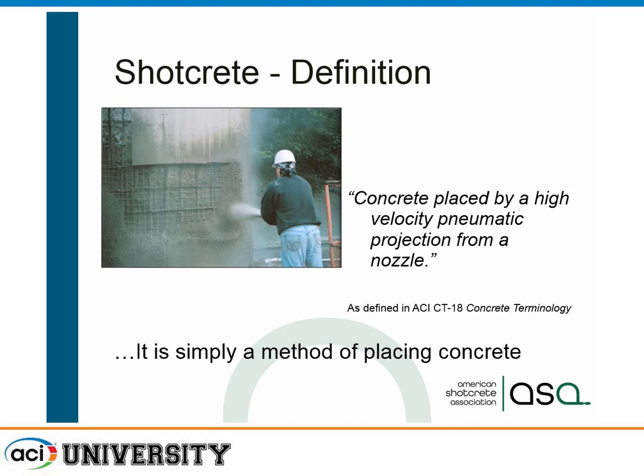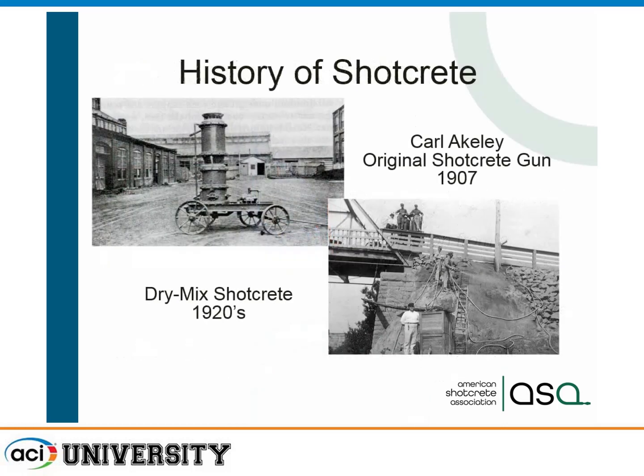It's pneumatically taking concrete, placing it at high velocity. When we say high velocity, we're talking 60 to 80 miles per hour. So if you think about it, if you're driving down the freeway and you hit a concrete column at 60, 80 miles an hour, that's a ton of impact, isn't it? That's what we do with every square foot of concrete that's placed by the Shotcrete method. That's how we get consolidation. That's how we get it driven in place so that it can hang not only vertically, but on overhead surfaces.